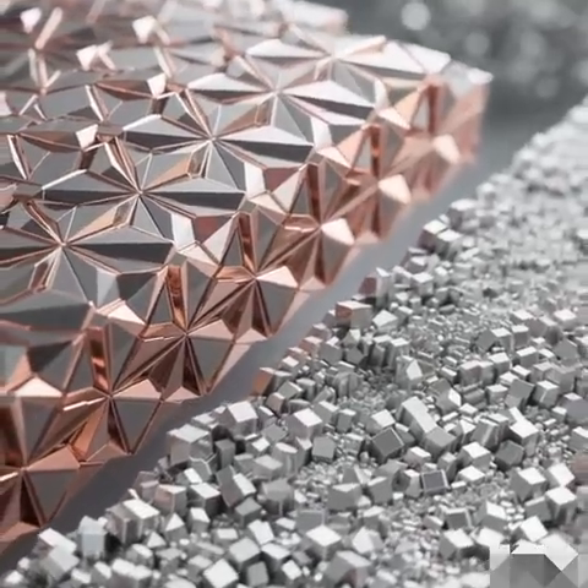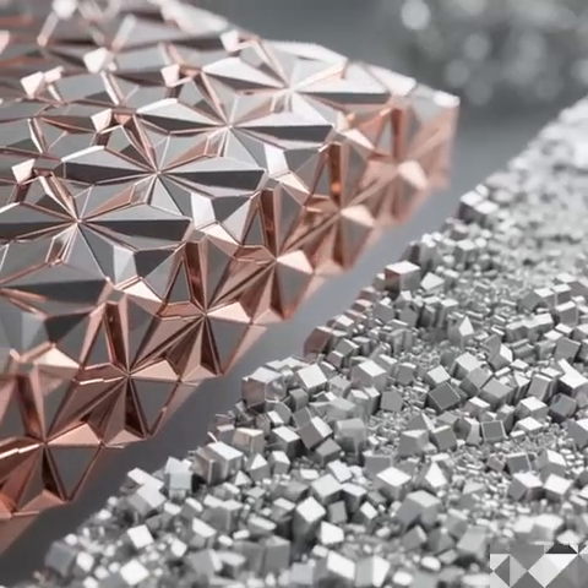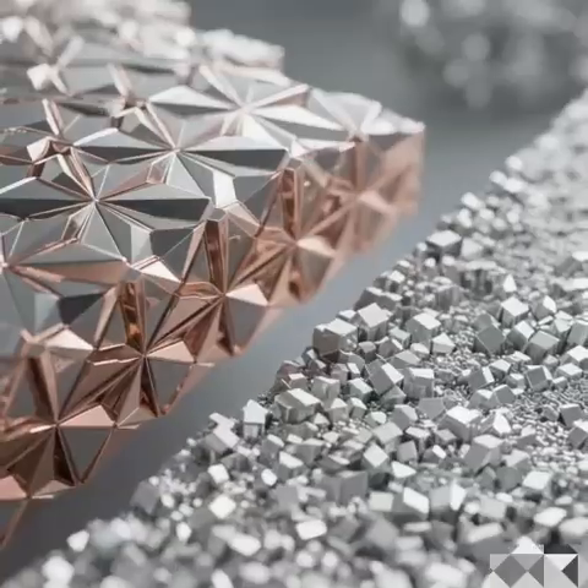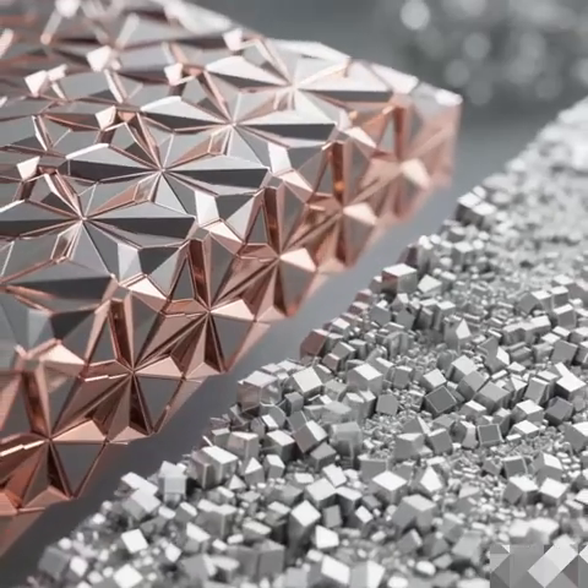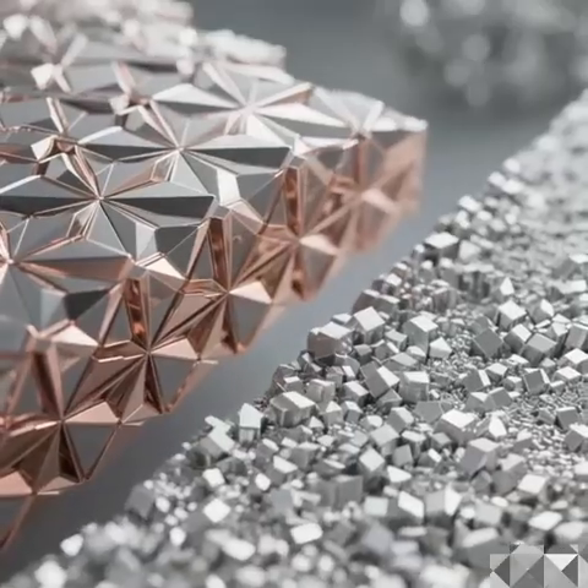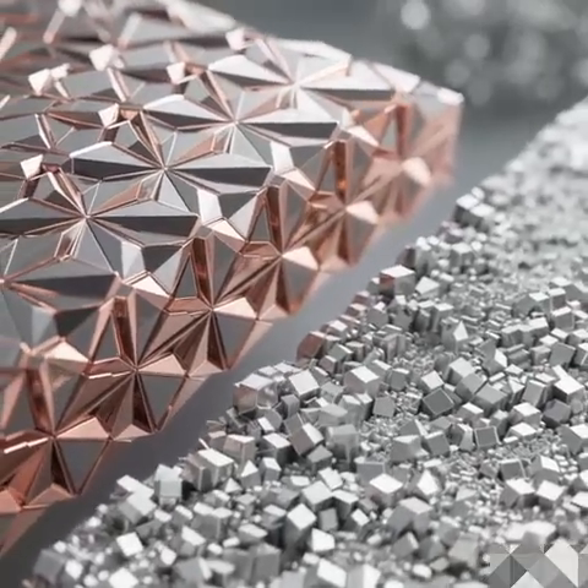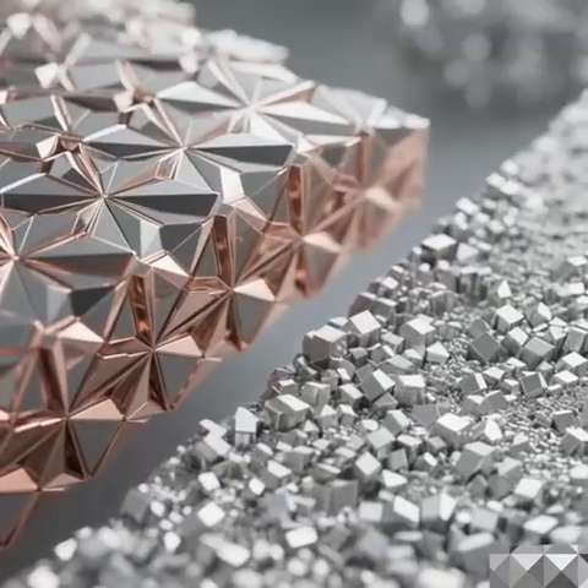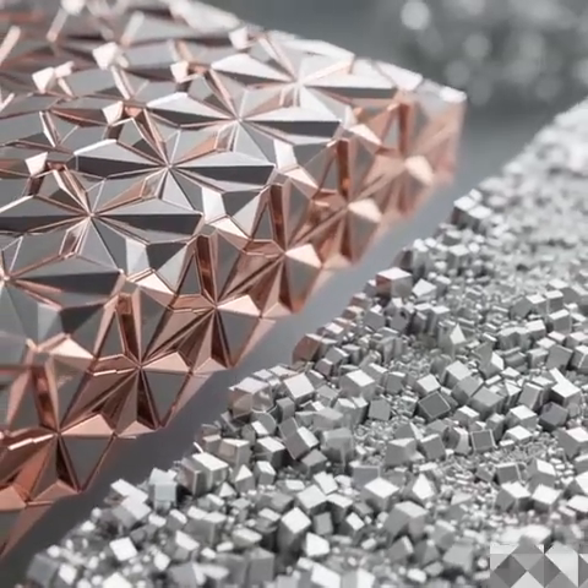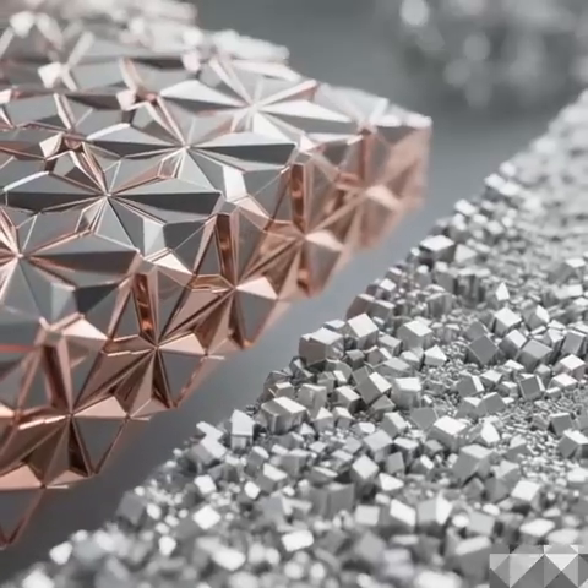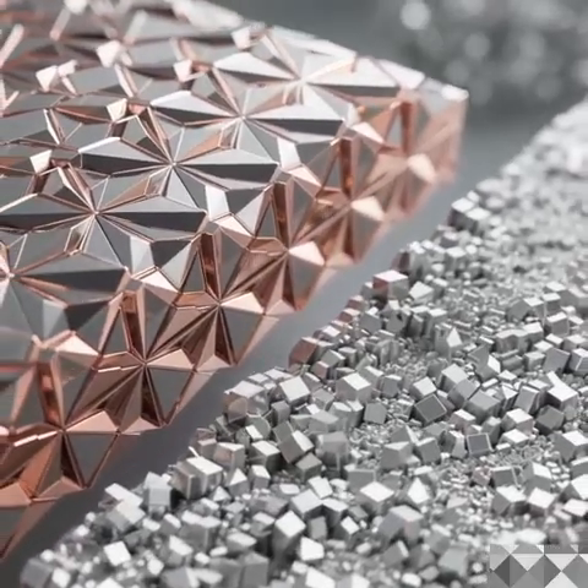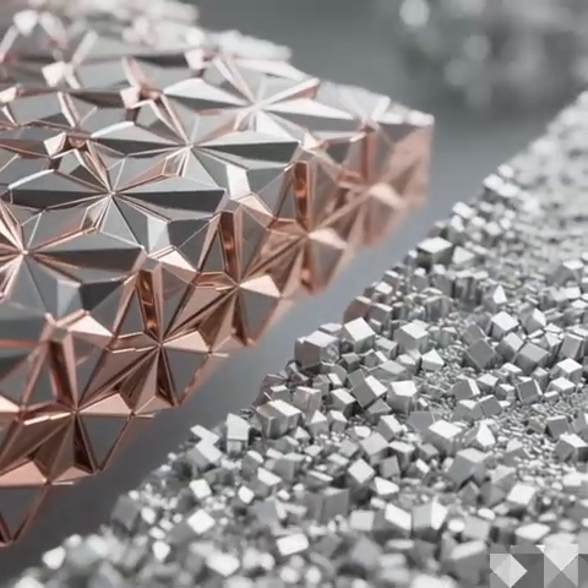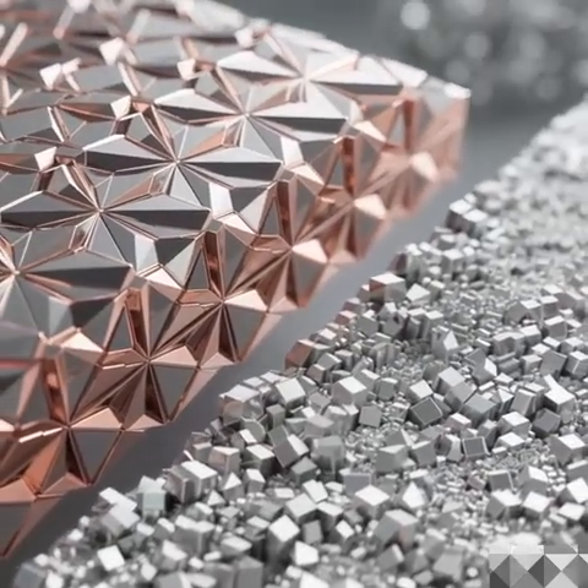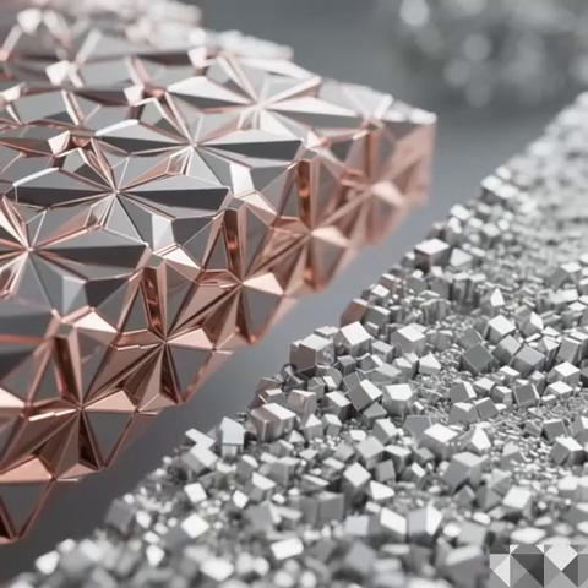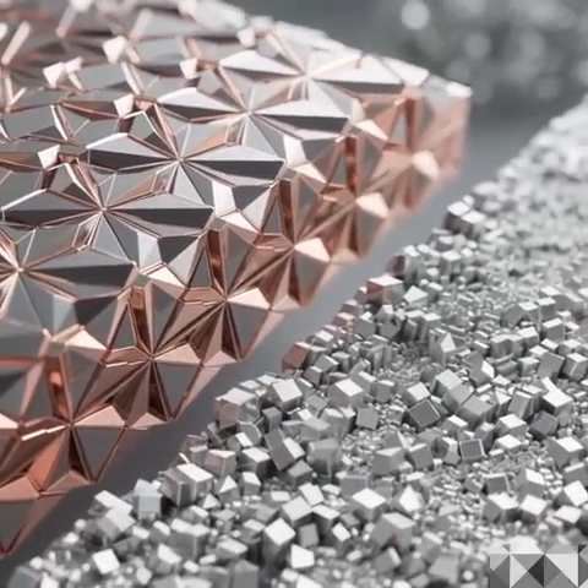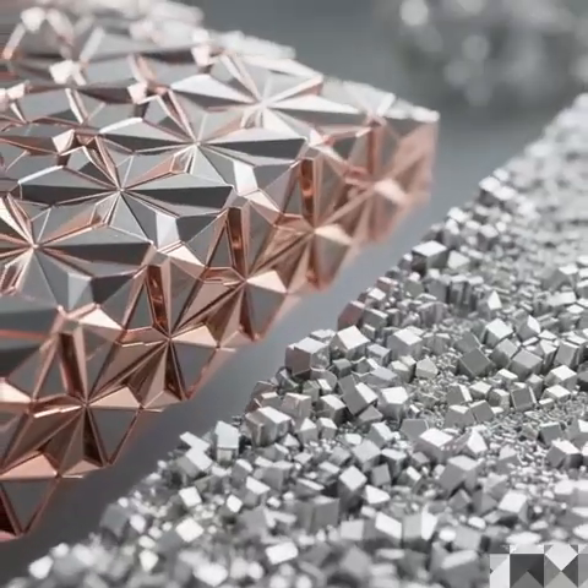Okay, so let's start with the first one then. Nanotwinned copper, NTC. Its microstructure sounds really unique. You hear about these highly 111-oriented faces and these vertical twin boundaries, very dense ones. That's right. Think of those twin boundaries like, we mentioned atomic scale mirrors earlier. That's actually a pretty good analogy. They're incredibly ordered, very low energy planes within the crystal structure, not just random defects. So they're structured pathways. Essentially, yes. Calming superhighways. And the 111 orientation, that specific crystal face, is crucial.